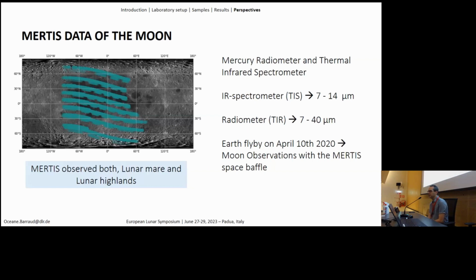MERTIS is a sort of double instrument. It is a thermal infrared imaging spectrometer that covers 7 to 14 micrometers. So you will see all these features that I was showing you: Christensen feature, Reststrahlen bands, transparency feature in the spectra. And then we have the radiometer, because of course we need to sound the surface temperature for calibration of the measurements. And as I told you, the flyby was 3 years ago.